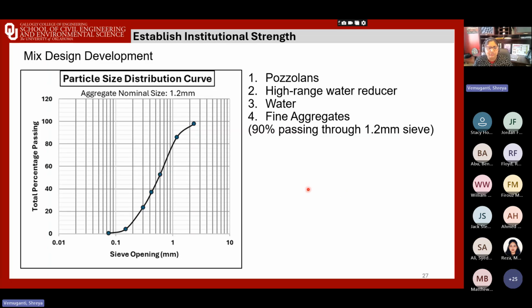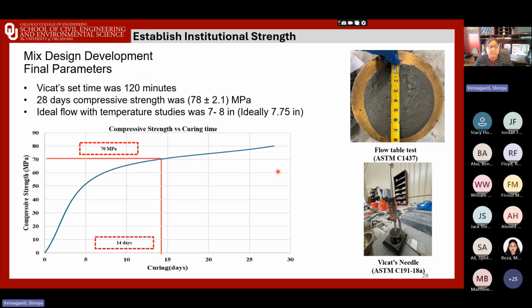And if you see, at least 50% is passing through 700 micron. So this was sort of a final mix, and the final parameters that we achieved through this mix: the Vicat setting time was 120 minutes. The 28-day compressive strength was about 78 MPa, like 11.5 ksi.